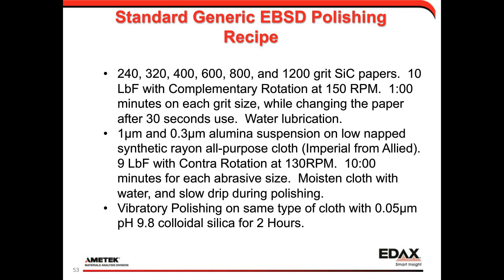The reason I do that is that with the more coarse abrasives, if I use contra rotation, it's a little bit easier for my machine to introduce a little bit of a bevel, or a non-planar front or back surface, onto the sample. Ideally, I want my back and front polished surfaces to be parallel because it helps keep my sample at the correct orientation that I expect. But I can switch to contra rotation at this stage because I'm not going to be removing as much material with these smaller abrasives.